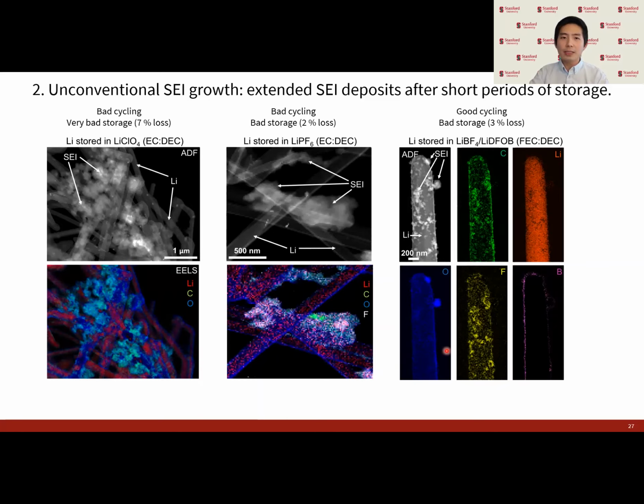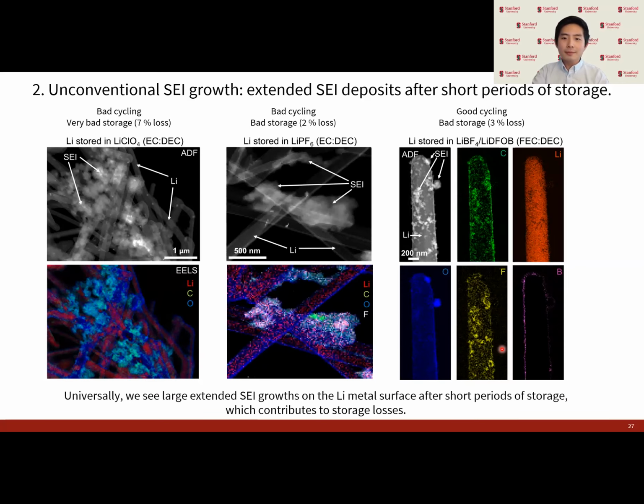And in the dual salt borated chemistry, so this is this BF4 and DFOB salt, we can see that the extended SEI is mainly rich in carbon, oxygen, and fluorine. But the boron's primarily relegated to this compact SEI film. But universally, all these lithium metal electrolytes are bad to varying degrees during storage, and all of them do show these extended SEI growths.